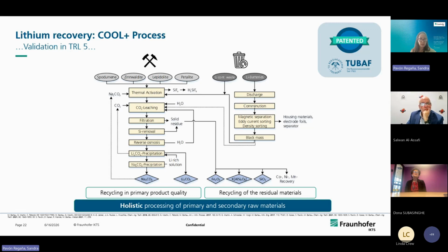From the primary side, we usually need a thermal activation in order to change the phase of, for instance, spodumene from alpha spodumene to beta spodumene, so that the mobilization and the recovery of lithium is more available. From batteries, what we are doing is first a discharge, then mechanical treatment, crushing, grinding, sorting in order to have the black mass. The black mass is where all the valuable metals are placed: cobalt, nickel, manganese, lithium, and also graphite.